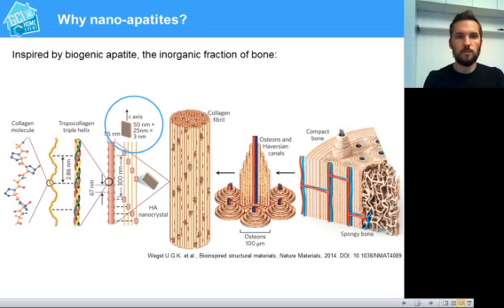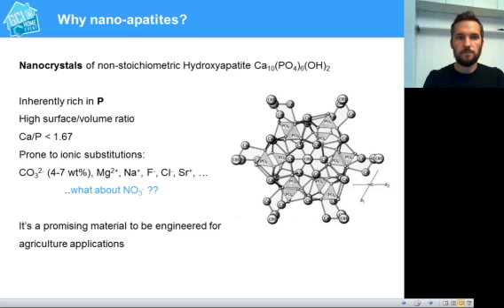In fact, we were inspired by biogenic apatite, which is the inorganic fraction of bone, to design a new type of fertilizer, a smart fertilizer, much more efficient than the conventional ones. And this is obtained with this nanocrystalline phase, which is much less soluble than the conventional fertilizers, but inherently rich in phosphorus and prone to ionic substitution, in particular carbonate, which is the major one, but other ions can enter the structure. So we explored the possibility of introducing nitrate within the structure of apatite, making this a promising material to be engineered for agricultural applications.